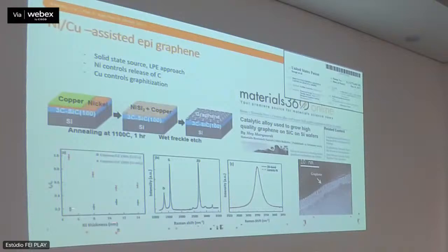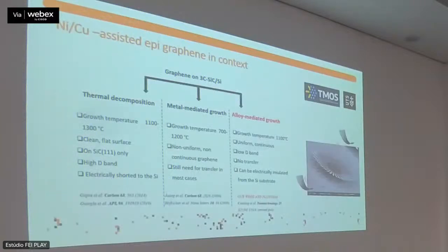This is a spectrum that relates to this point here. And what that means is that we don't have large grain sizes. We have grain sizes of about 100 nanometers, but it's a continuous and uniform layer of single-layer graphene, which is what we want. And I'll come back to the grain sizes. You will find out that in quite a few instances, this is a good thing to have. Surprising. So basically, if you want to think about our process in a different way, we are in a hybrid between thermal decomposition, where we use carbon and silicon carbide but don't go to the same high temperatures, and metal-mediated growth, where people do CVD growth on, for example, copper or nickel foils, and then have to transfer the flakes.